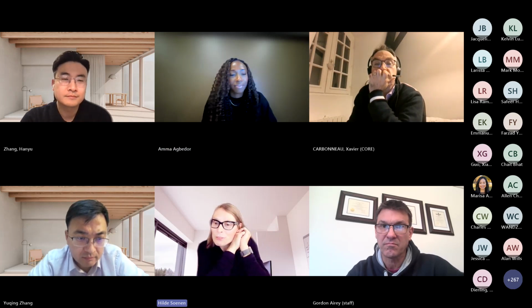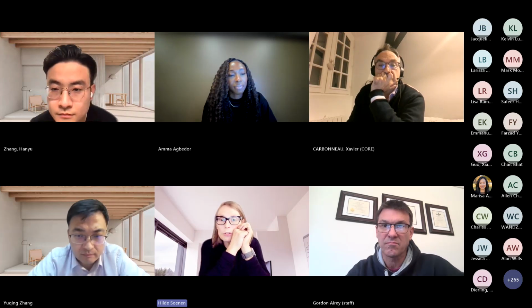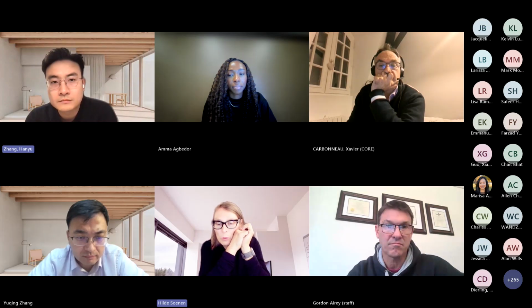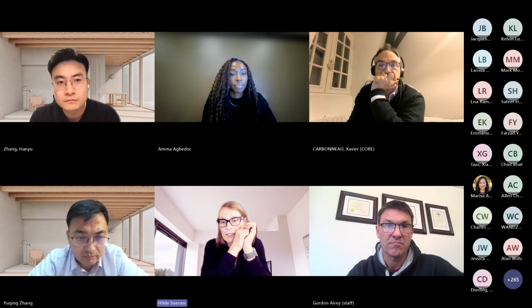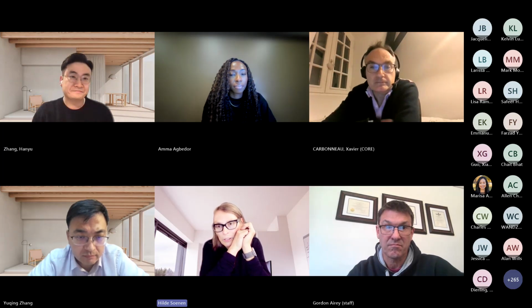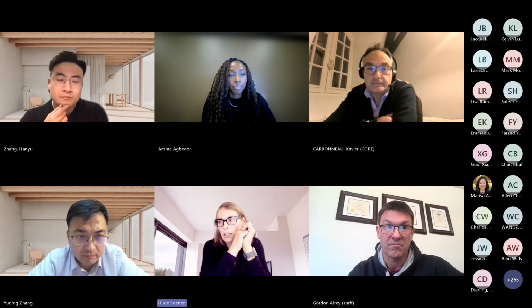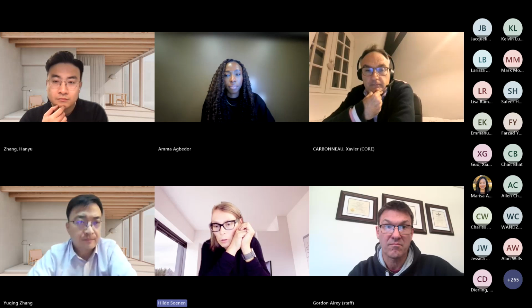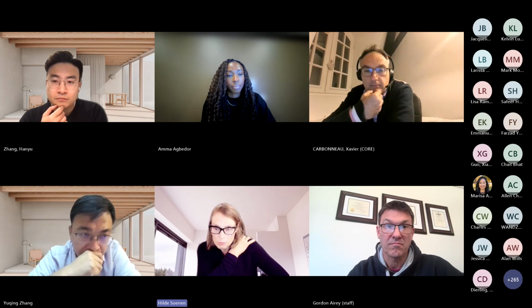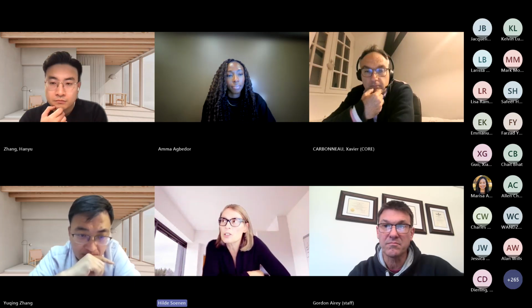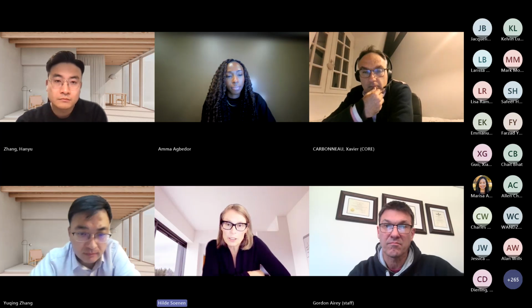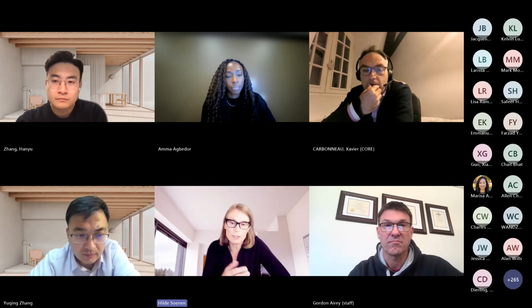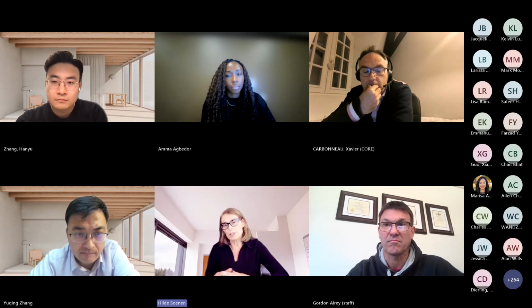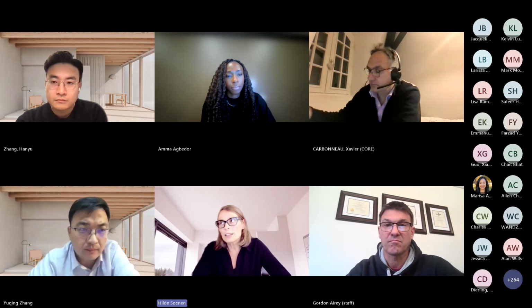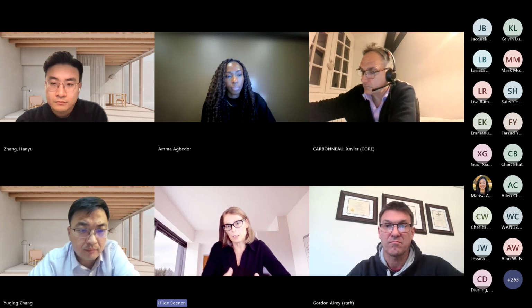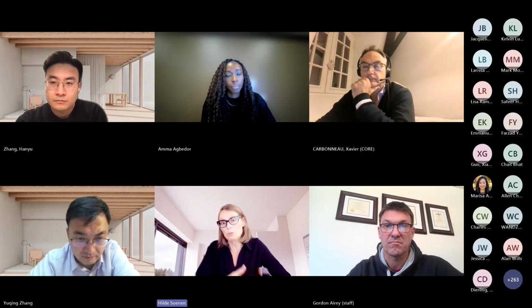Okay, maybe I will start with the first part of the questions. Finding a new aging method was in fact out of scope of the project, but maybe it's more my personal view. I think the temperature should be as low as possible, but there is a rule of thumb: if you decrease the temperature by 10 degrees, you have to double the time. So of course you can't go too low in temperature because it will take a lot of time. But at least from the project, we had indications that at higher temperatures the sulfoxides disintegrate, and if they disintegrate, probably they increase the aromaticity of the system. We noted that larger aromatics are formed at higher temperatures, and these increase the stiffness at higher temperatures, but not at lower temperatures, and that's why we saw the discrepancy.